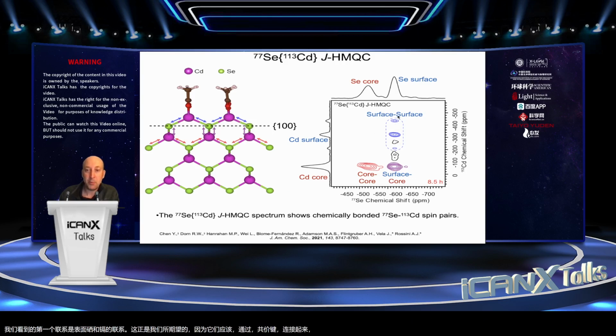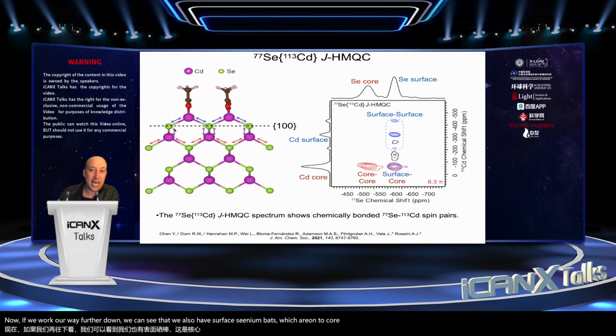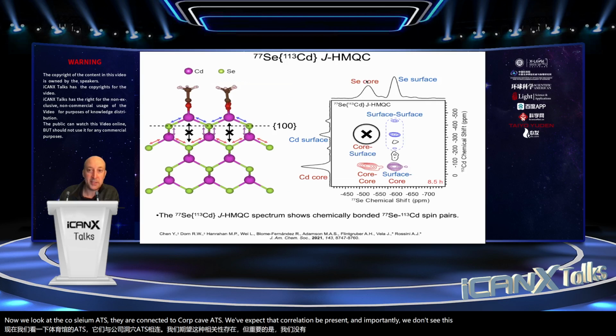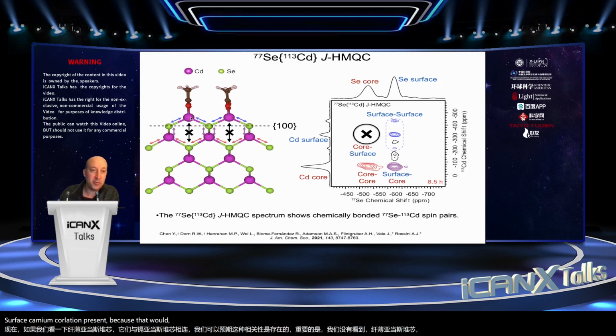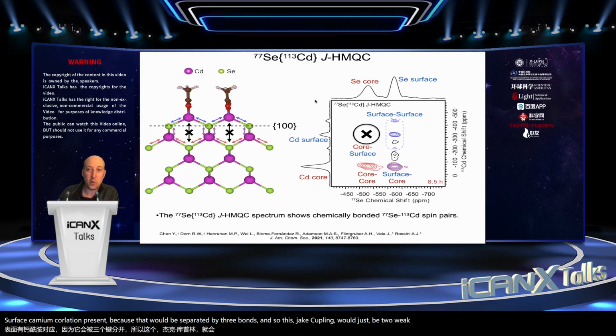Now, if we work our way further down, we can see that we also have surface selenium atoms which are bonded to core type cadmium atoms. That makes sense. Now, if we look at the core selenium atoms, they're connected to core cadmium atoms. We would expect that correlation to be present. And importantly, we don't see this selenium core surface cadmium correlation, because that would be separated by 3 bonds. And so this J coupling would just be too weak to give a correlation in this experiment.